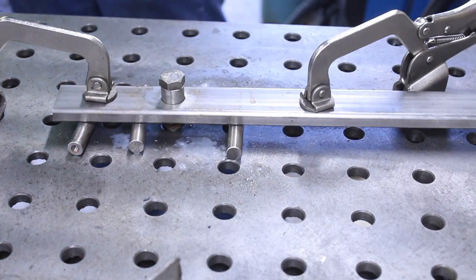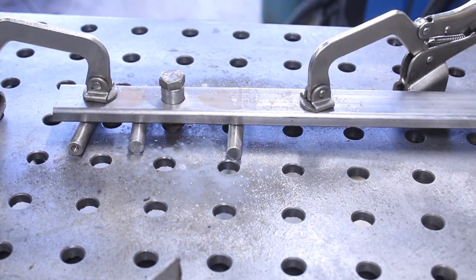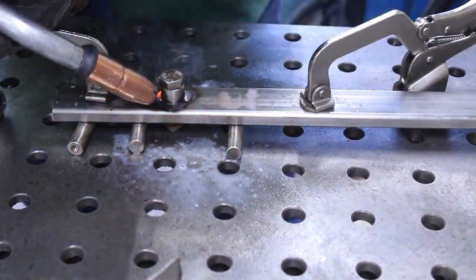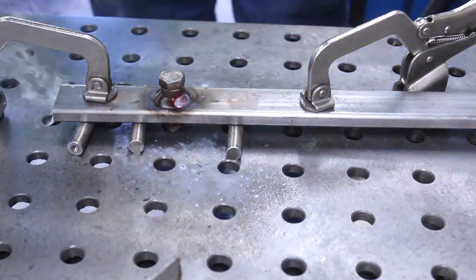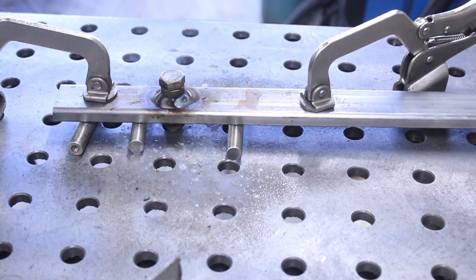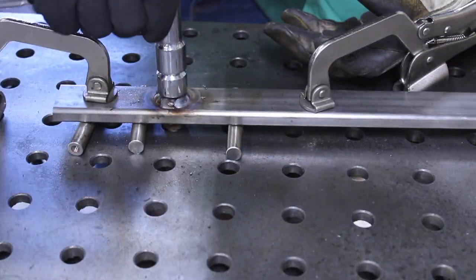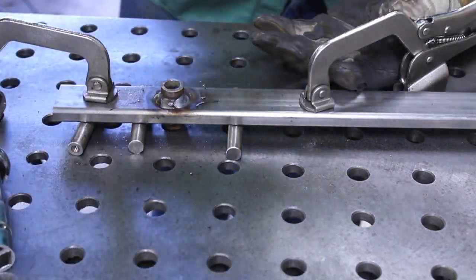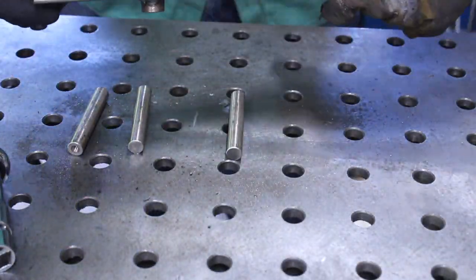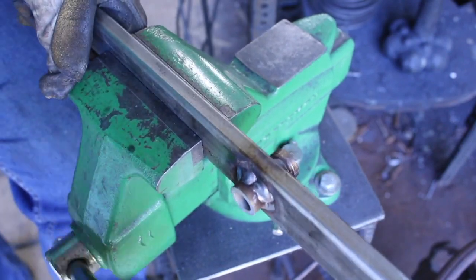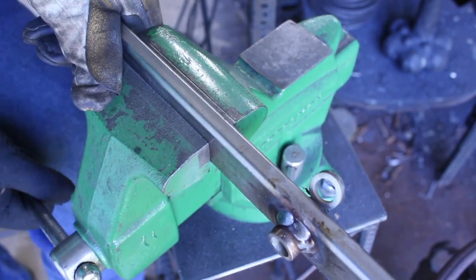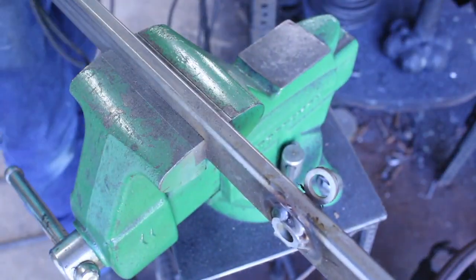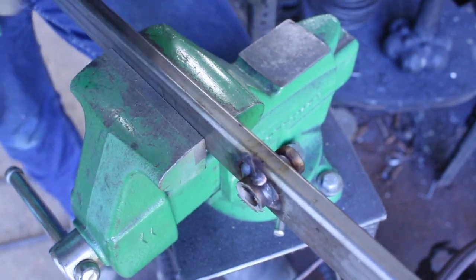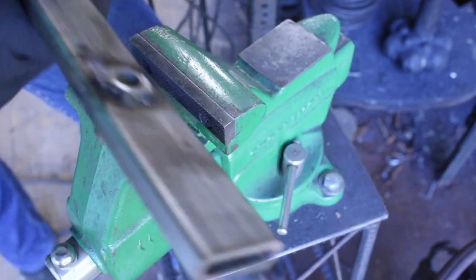But with stainless alloys, we can see some defects that form rather readily. One most notably is cracking. Because austenitic steels lack ferrite, which dissolves and homogenizes detrimental impurities that result in cracks, you see an increase of this defect similar to high carbon or even alloy tool steels. And there are ways to prevent this, first by decreasing outside contamination, second by controlling the heat affected zones as much as you can, and third intrinsically by selecting a filler material that contains higher ferrite to mitigate or even dissolve those detrimental impurities. You do have some things against you with austenitic stainless steels.